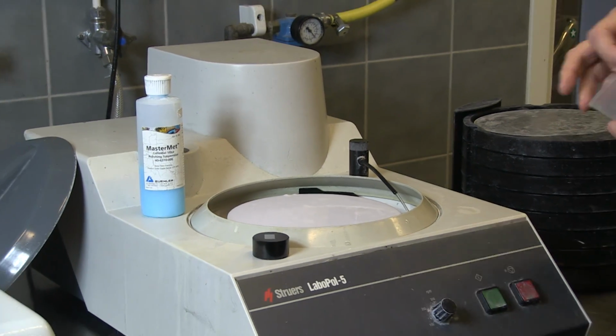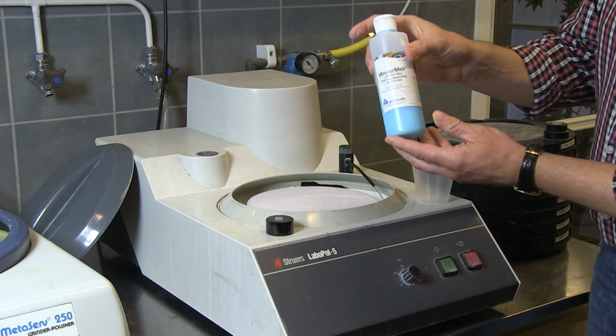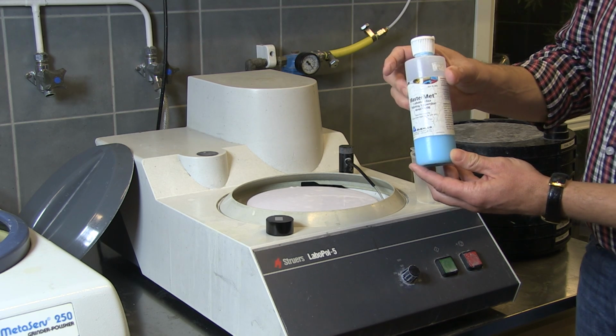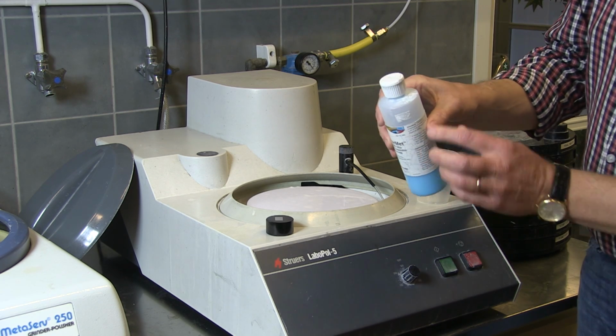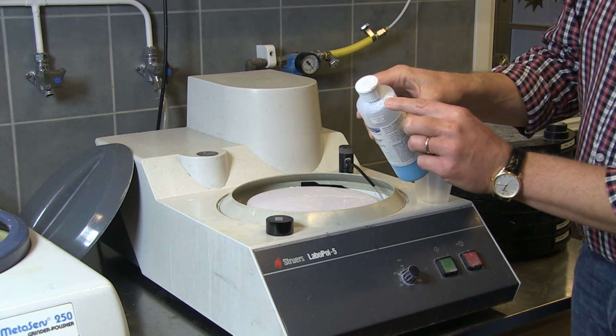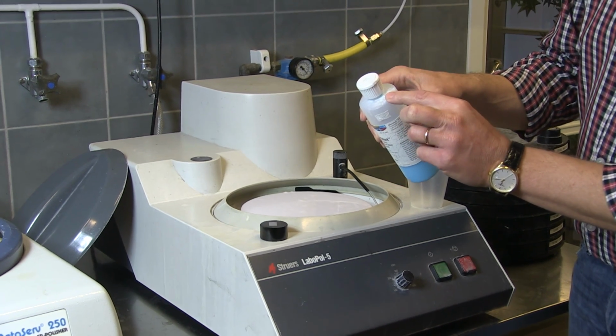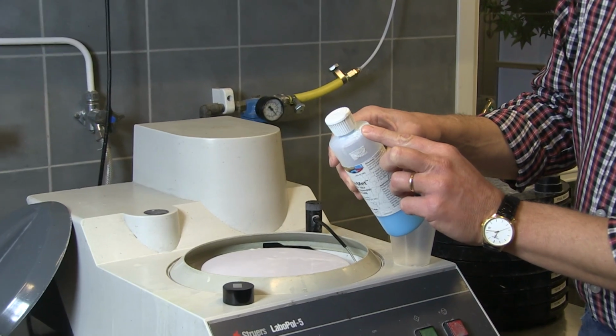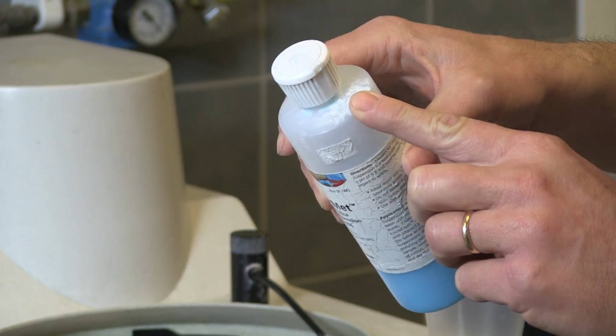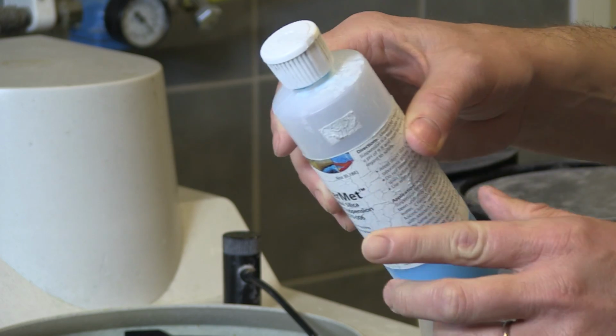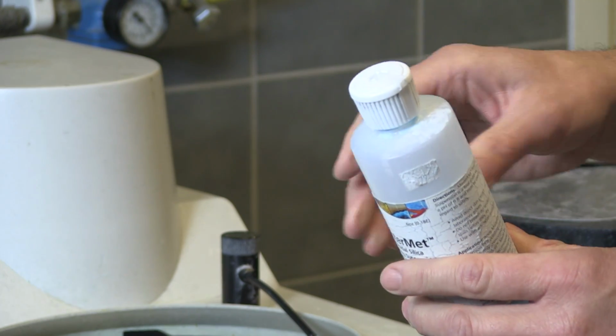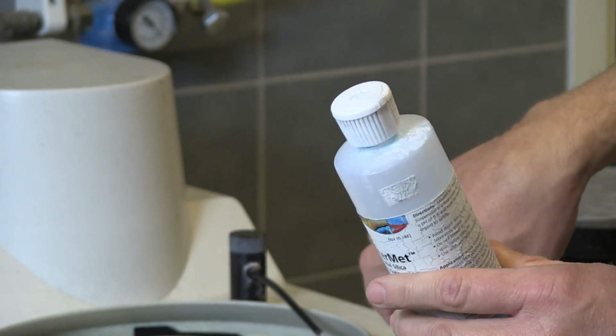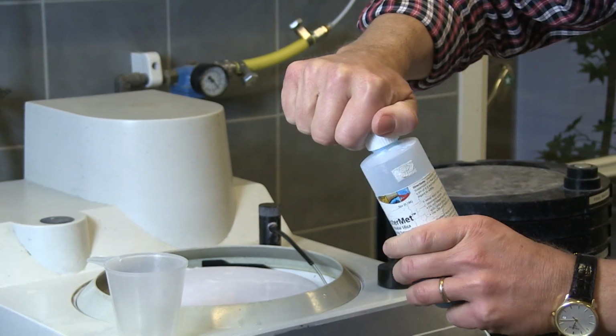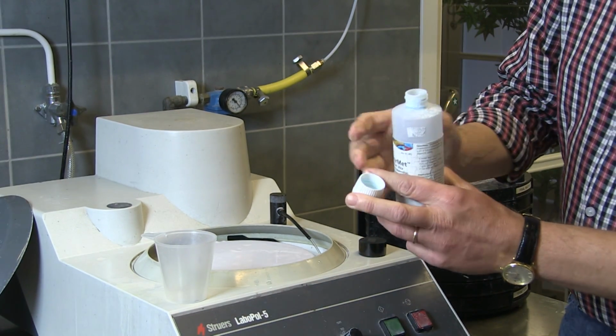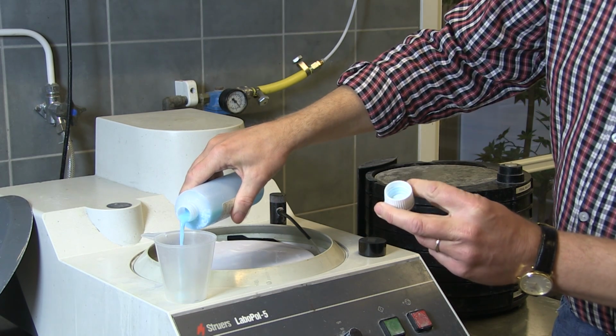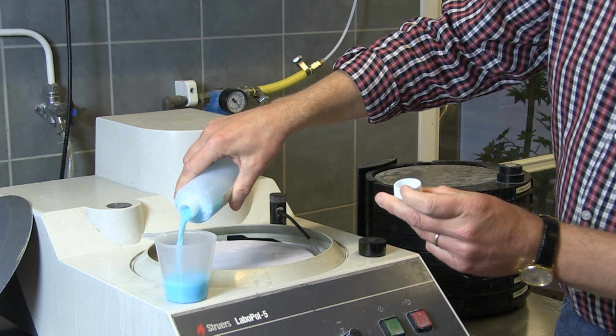This suspension here is, as I mentioned, very, very sharp, small particles, but it also dries a little bit here under the cap and on the neck here. And these dry particles can be much, much bigger than 0.06 micrometer. I'm not sure you can see them. So to avoid getting them on the cloth, we don't spray it. We fill it in a cup, like that.